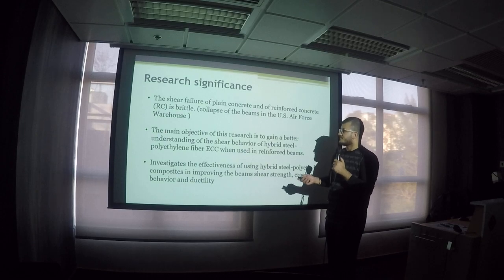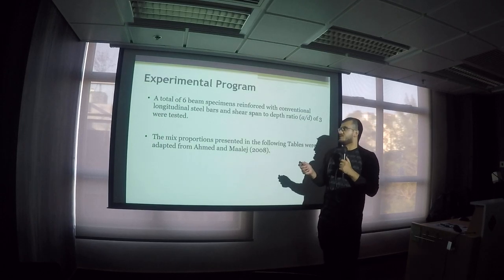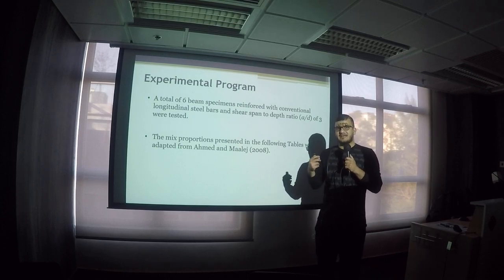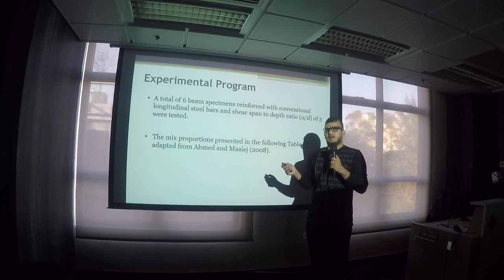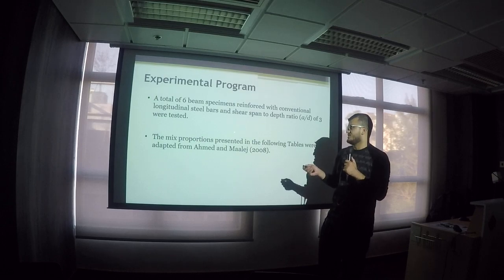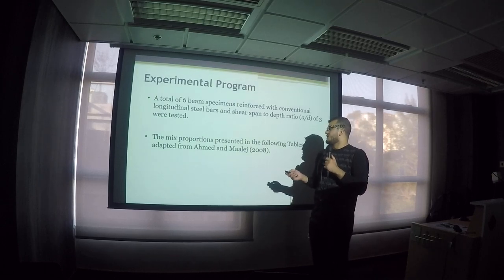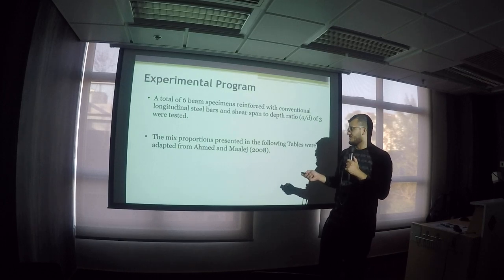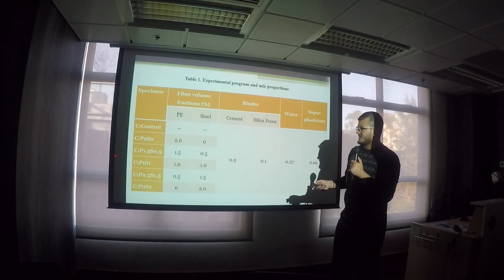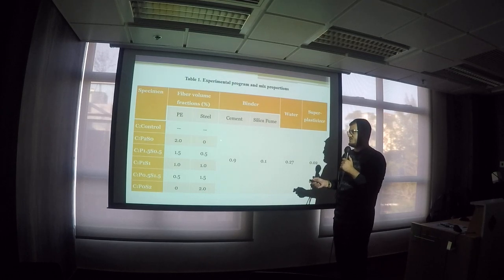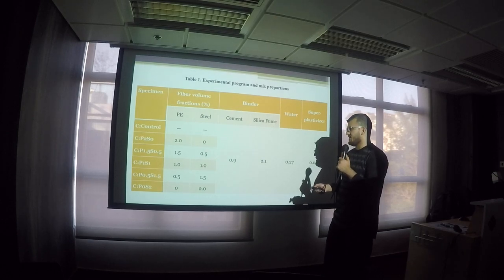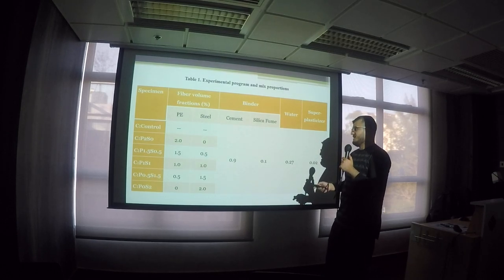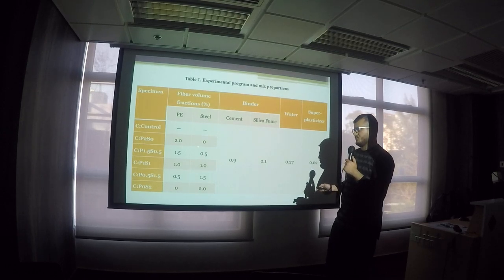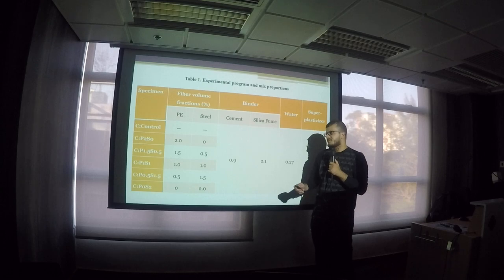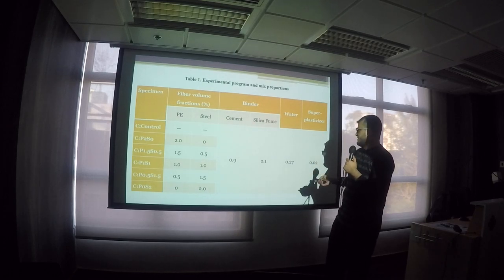So in this program, 6 beam specimens were cast and tested under an a/d ratio of 3, which is the shear span over the depth ratio. The mix proportion used was adapted from previous research. As you can see here, here are the 6 beams. The first one was a control beam with no fibers at all, while the rest have a combination of hybrid steel and polyethylene with a maximum volume fraction of 2%, as you can see here. And this is the mix design.